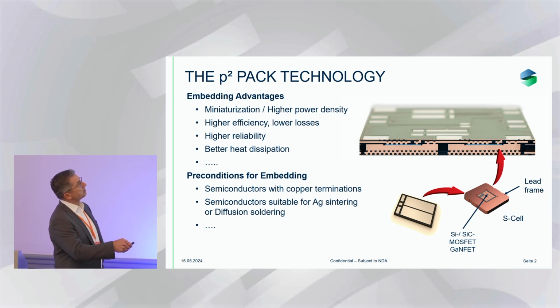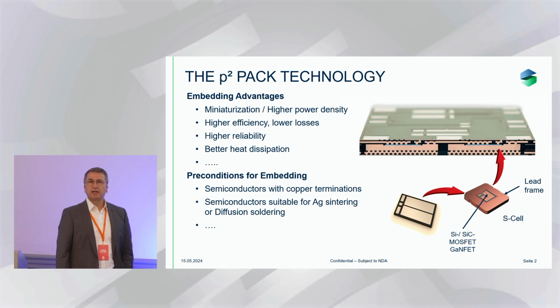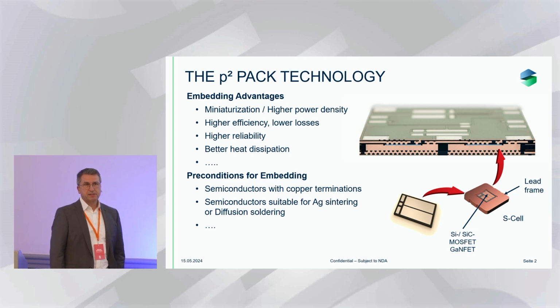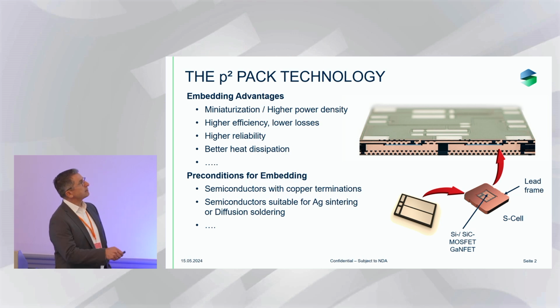So what you see here is a half-bridge design. The connection is done from the drain to the source directly, so this would be your phase contact point. What you can also see is that at the bottom of the standard cell, during production, we implemented 2 levels of copper-filled microvias. The reason for that is to improve the thermal conductivity from the device to the outside